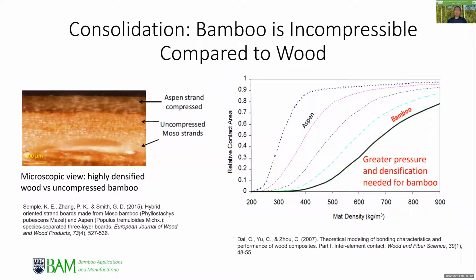The other area is how bamboo is consolidated and brought together into a solid product. If you compare that with wood, very little compression can occur, compared to the high densification of wood in the same piece of hybrid product. The goal of pressing, whether with bamboo or wood, is to bring the pieces together to create intimate contact. With increased density you will have an increment of contact, but because of the natural density of bamboo, it takes much greater pressure and densification to create a significant bond.